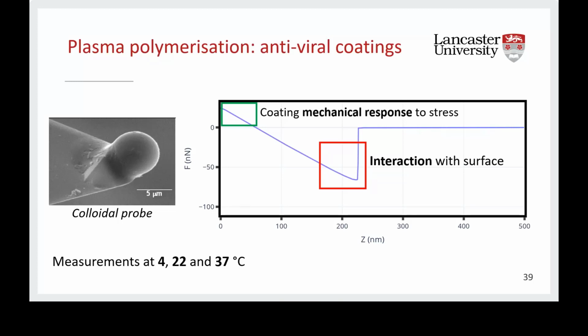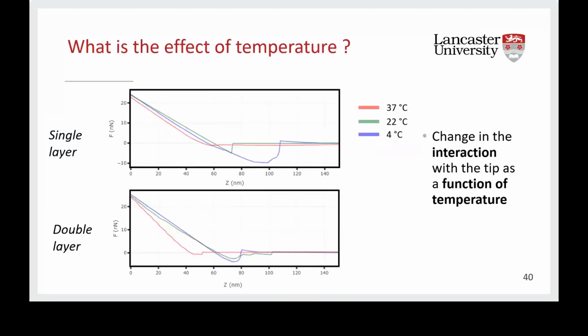I prepared some sample holder for the AFM to perform this kind of measurement at 4 degrees Celsius, 22 degrees Celsius, and 37 degrees Celsius in water environment to replicate the antiviral testing environment. So, here you can see the results. In the first graph, there is a single layer.